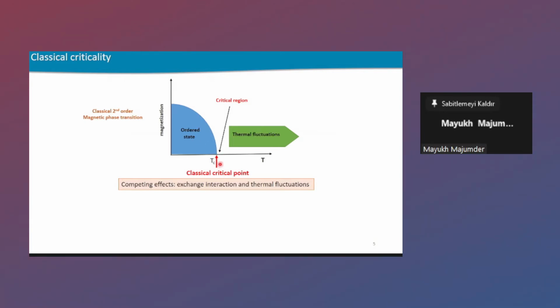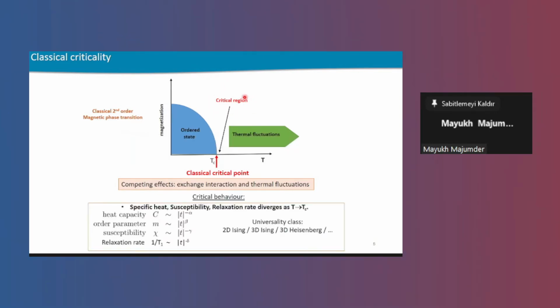As you know, for a classical second order magnetic phase transition at higher temperature, you have thermal fluctuations dominating over the exchange interactions between the electrons. But below a certain classical critical point, the system orders into a magnetically ordered state where the exchange interaction is winning over the thermal fluctuations. Just above the classical critical point, you see some sort of critical regime. In that regime, you would expect physical parameters, for example specific heat, susceptibility, and relaxation rate evaluated from NMR or muSR, all to diverge towards the ordering temperature, and all these diverging properties follow some sort of power law behavior.